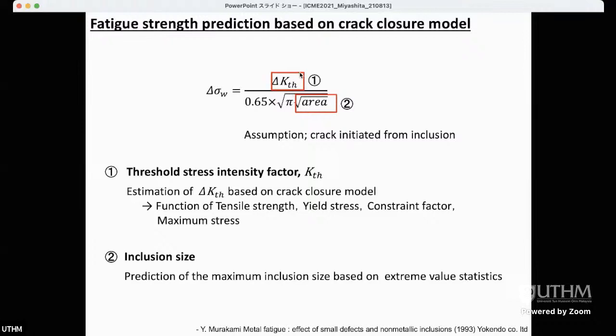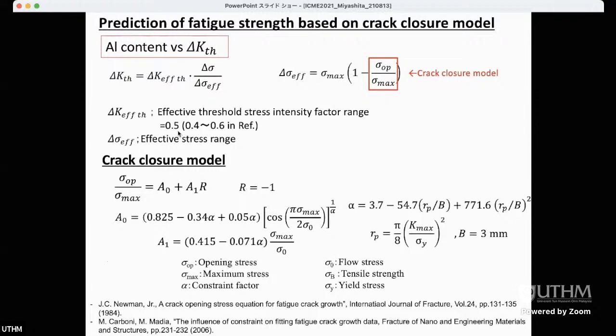And also for calculation of delta K threshold, we use the crack closure model. So in order to obtain this delta K threshold value, we need to obtain another parameter, as you can see from this equation. The effective threshold value is almost 0.5 according to the reference, so we can assume 0.5 in this calculation. And delta sigma is applied stress, so we can change it, of course. And we need to obtain this delta sigma effective stress range.